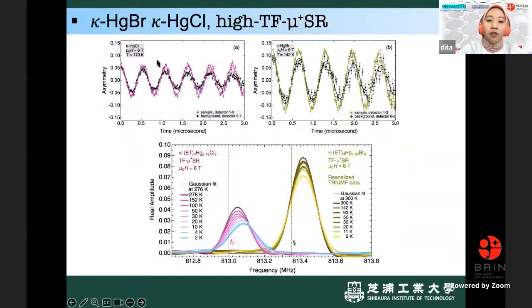Okay, this is the spectra for the chlorine and the bromine sample. Maybe it's easier to see if I plot with the rotating frame, because at 6 Tesla it's very difficult to see without the Fourier transform. So I can show you the Fourier transform after the transformation. You can see here for the bromine, there is no shift. If you compare with this central line, it's almost the same spectra for the bromine, but for the chlorine, you see there is a shift by lowering temperature here.